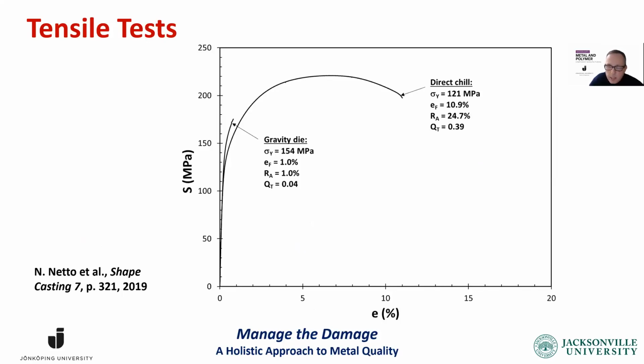You can excise a tensile specimen. Here from the same ingots, we have 1% from the gravity die, and we have about 10.9% from the direct chill casting. When we look at the quality index, one has 0.04, the other one has 0.4, which means it's 10 times better.